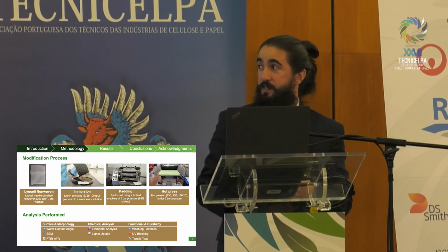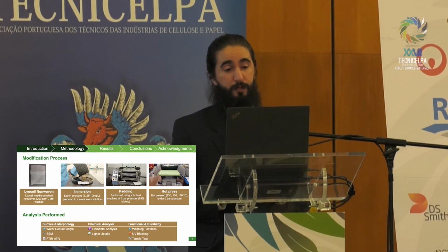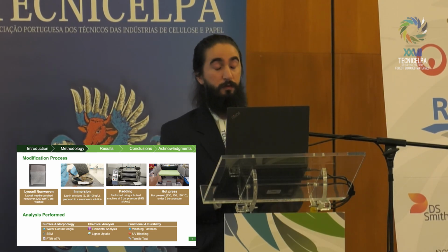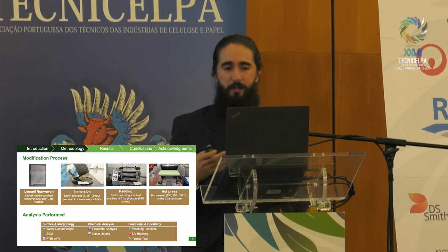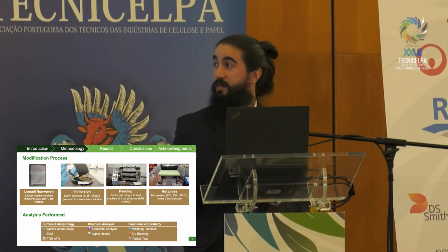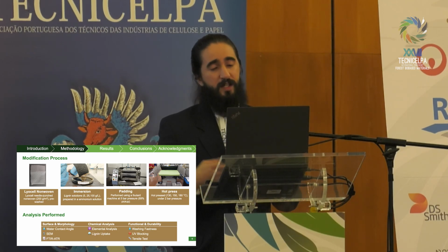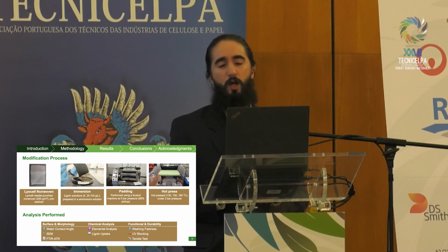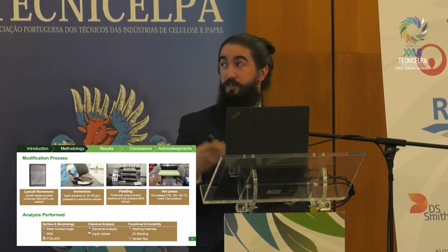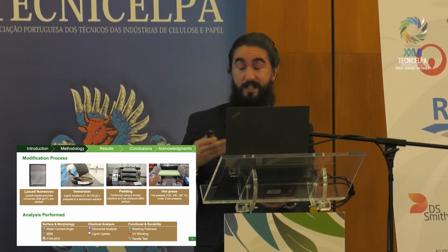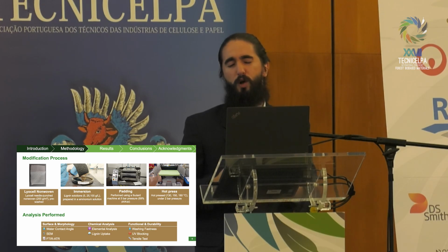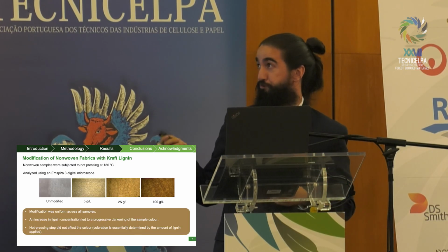In terms of analysis, we divide them into three groups. First, the surface and morphology. We assess the water contact angle, also some SEM and FTIR. In terms of chemical analysis, we did elemental analysis and lignin uptake by extraction with sodium hydroxide. And then in terms of functional and durability, we assess the washing fastness with successive washings, and also UV blocking and tensile tests.